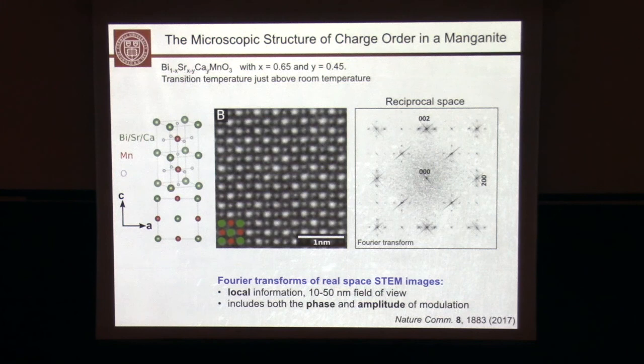So here, maybe 10 to 50 nanometers or so in standard diffraction imaging. And that tells you that over 10 to 50 nanometers, you already have these two orthogonal order parameters, one in this direction, one in the orthogonal direction. The other advantage is not only do you measure relatively locally, but you also have both phase and amplitude of the modulation. Okay, and that will become important in a minute.